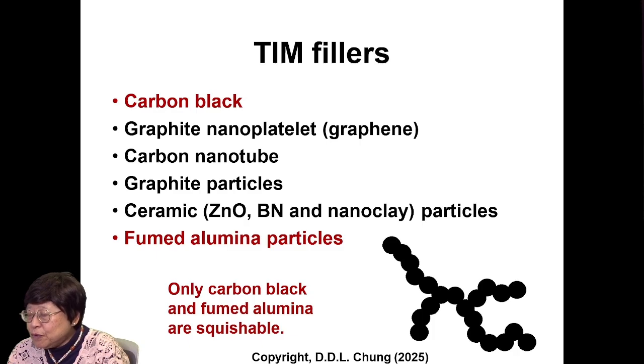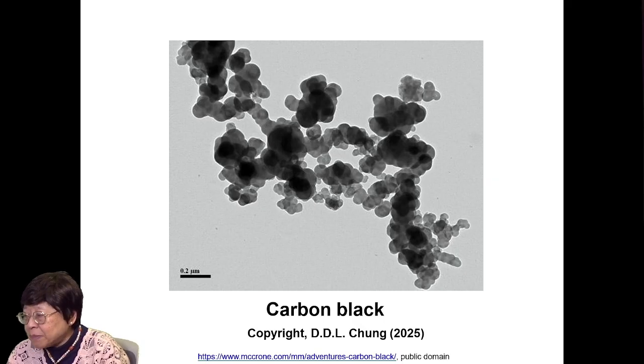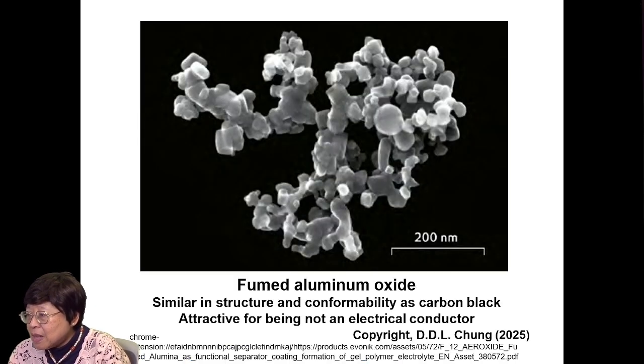Carbon black and fumed alumina both have the morphology of aggregates of nanoparticles. So these two are the only two in the list that are squishable. All the others are not squishable. This is the carbon black, aggregates of nanoparticles. And this is fumed aluminum oxide, also in the form of aggregates of nanoparticles. So the fumed aluminum oxide is similar in structure and conformability as the carbon black, and it's attractive for being not an electrical conductor.